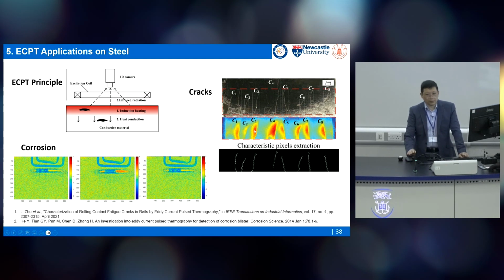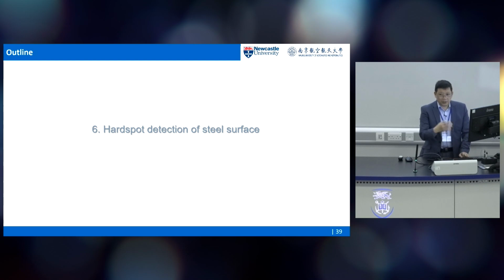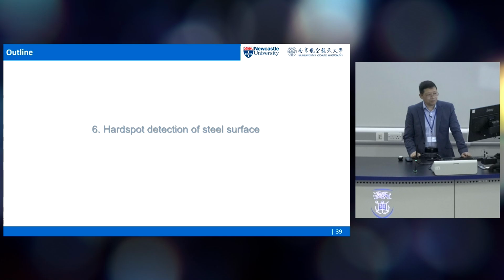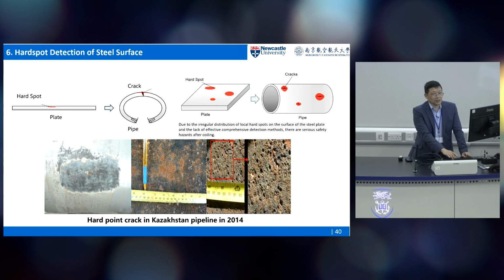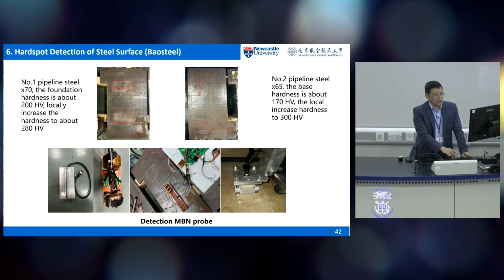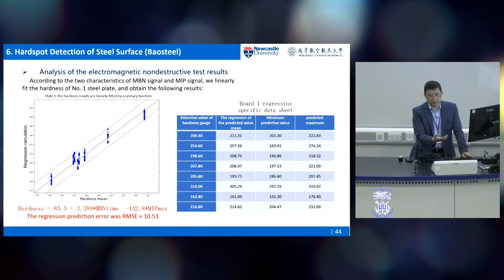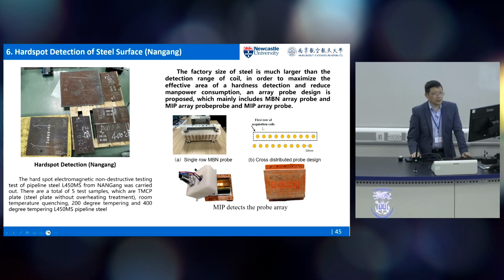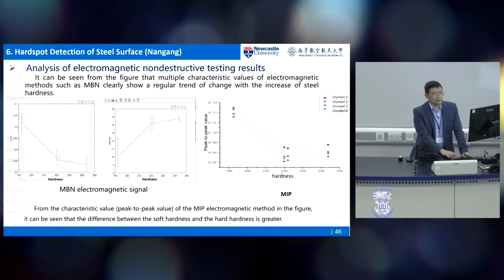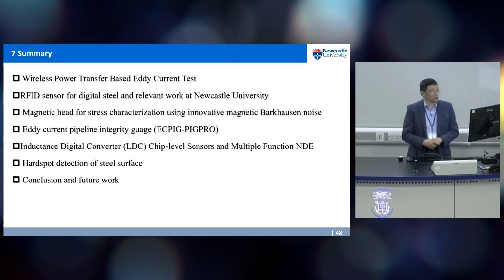For example, we can apply this for high-speed railway to measure the rolling contact fatigue of rail track. So finally, we integrate different kinds of approaches to tackle a big problem for the steel industry: hard spot detection. Because this kind of defect or stress concentration is quite small, how can we do that? Again, as we mentioned earlier, we use a high spatial resolution probe and a sensor array, and with different combinations, we can use magnetic Barkhausen noise, combine it with the eddy current, and design different kinds of sensor arrays for different applications.